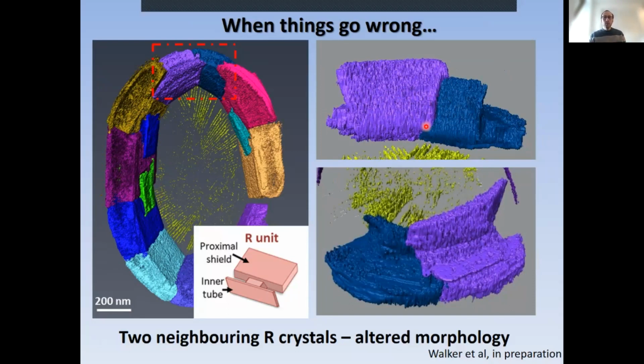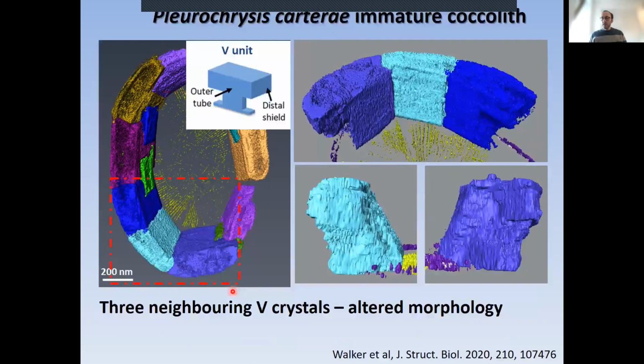They're just growing without any restrictions to the top and to the bottom, which indicates that the presence of a V unit here in the middle would be very important to restrict the growth and basically bring about this anvil kind of morphology. And you can see the same thing in a region where we have three V units